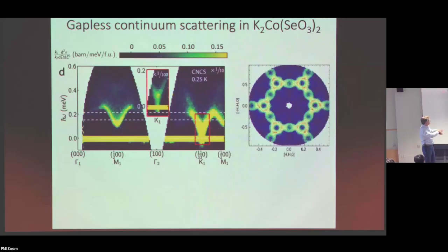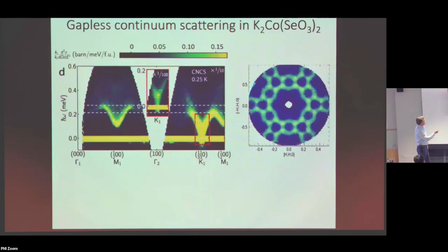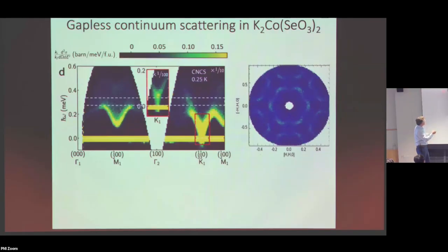And then as you come even higher, this whole thing comes together, and we have these images almost looking like ARPES data. And you can keep going, and then eventually you go beyond this lower edge of the continuum, and you get into a region where you still have intensity. These are complicated features living at higher energy transfer, all the way up to 0.4 millielectron volt, which is way beyond the strength of the transverse interaction. It's about twice the strength of that, but you really have a continuum of scattering with some accumulation of intensity along the low energy ridge.